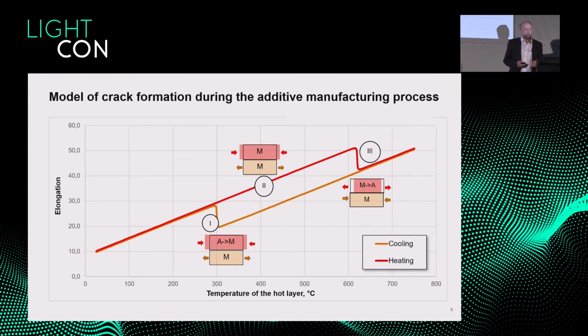The other one is a maraging steel, the 2709. It has a low carbon content, good weldability therefore, and in this case the martensite is soft because there's actually no carbon in this phase, so carbon hardens the martensite. So the stress in case 2 is limited for this 2709, so this is a good grade for additive manufacturing.